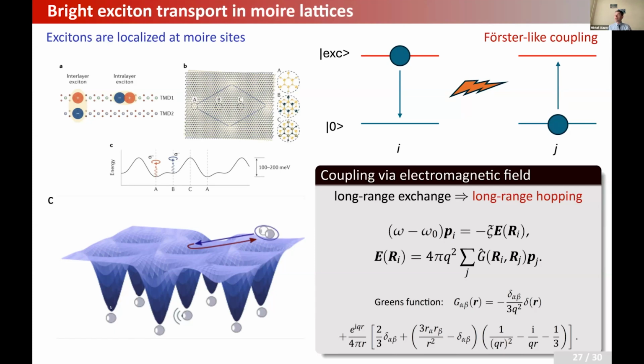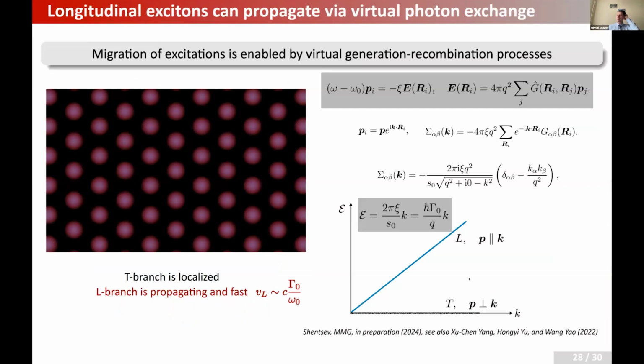And quantum mechanical tunneling is actually strongly suppressed in that case. However, because of this long-range exchange interaction, you can have a kind of long-range hopping between the localization sites. You can also interpret it in the form of Förster-like coupling. So the exciton at one site recombines, and it creates the electromagnetic field that propagates, and then it creates the exciton at the other site. You can map this problem to a problem of dipoles interacting via the electromagnetic field, and you can, of course, easily calculate the spectrum.